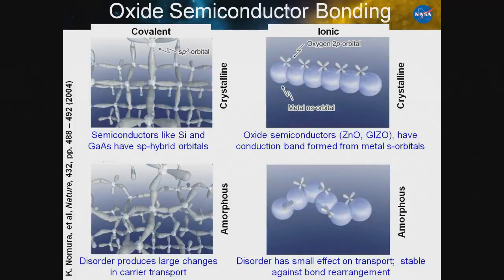The key to the zinc oxide thin film transistors is that unlike silicon, where the conduction band is really associated with the sp3 hybrid orbitals of the silicon, these are very strongly directional orbitals, and as a net result, if you degrade the crystallinity, as would be typical for a silicon that was deposited at a low enough temperature to be integrable onto the flexible glass, you end up substantially reducing the electrical performance from mobilities of several hundred centimeters squared per volt second to somewhere on the order of 1 centimeter squared per volt second.